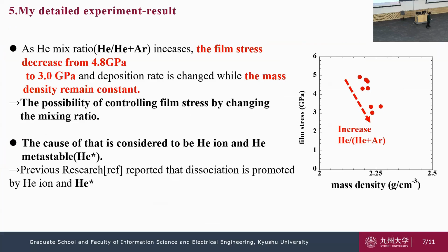As the argon-helium mix ratio increases, the film stress decreases from 4.8 gigapascal to 3.0 gigapascal. The deposition rate changes, while the mass density remains constant. This result shows the possibility of controlling the film stress by changing the mixing ratio.